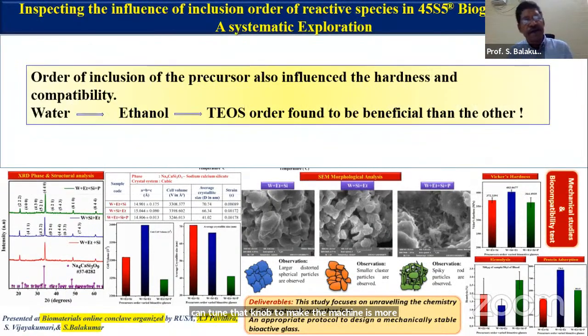Then we also studied changing the order of the precursor adding with a different solvent. That also has a huge impact, and you are getting many different, largely distributed spherical particles. There is a change in the surface area and in the biocompatibility studies, but all are within control. The only thing is how you can tune the knobs to make the materials more compatible. So we systematically explored how you can influence the hardness and the compatibility. We found that when you take basic water and add ethanol, that is also beneficial. Then there is the other way you prepare it, especially when you get the first silica matrix. So that is one of the studies.